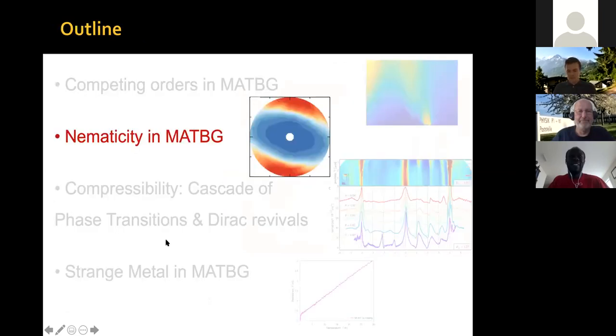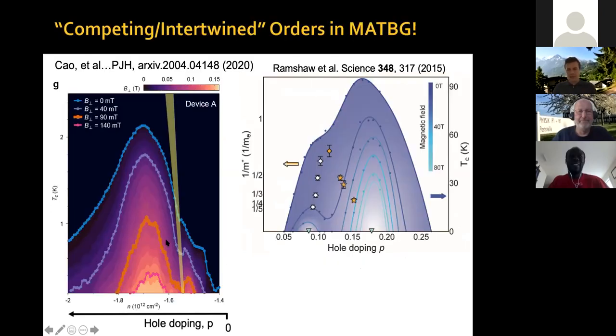So let me leave that there. I'm going to return to it, okay? There seems to be some competition between orders that leads to a depletion of TC within the superconducting dome in magic angle graphene at a doping of order 10% from the correlated insulator state.